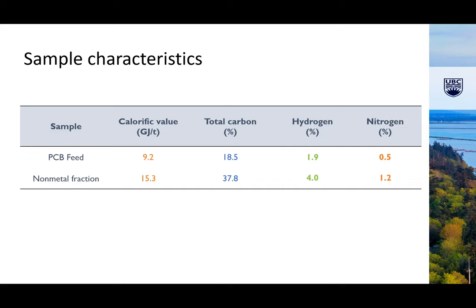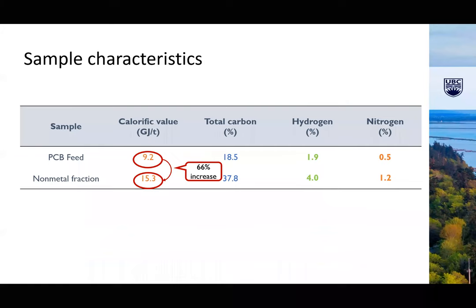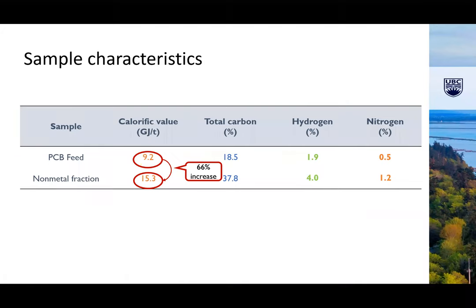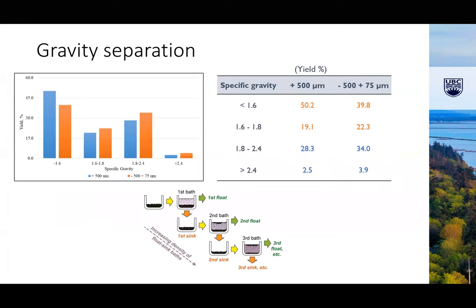So sample characteristics look like this. We had the PCB feed. So this is the e-waste material, which had 9 gigajoules per ton calorific value, then non-metal fraction almost double, because if it's organic, it does make sense. That's what it is in there. So there's already increase in energy value by the fact that we have all the organic materials in there.